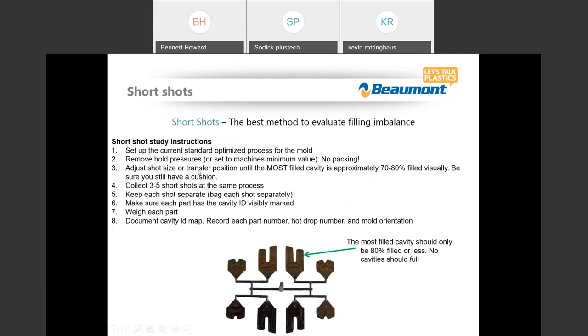So what we want to do when we look at short shots is fill our cavities to around 70 to 80% full visually. The first thing to do is establish a current, standard, optimized process for the mold. In other words, get the tool up and running like you would be in production. Then we're going to remove our hold pressures, or set those hold pressures to the machine's minimum value. So essentially, we're not packing these parts. We want first stage velocity control only at around 70 to 80% full visually. And then we're going to simply collect 3 to 5 short shots at that same process.